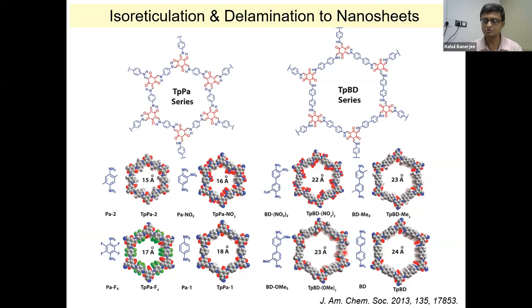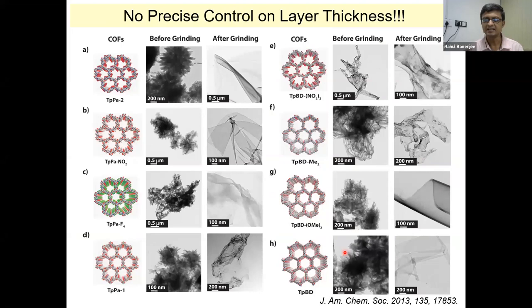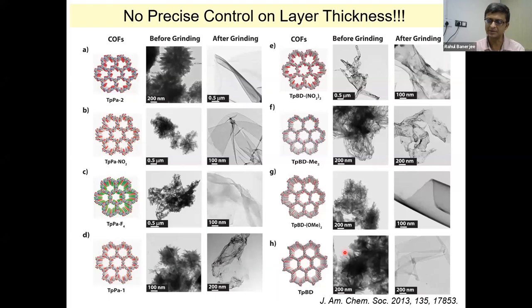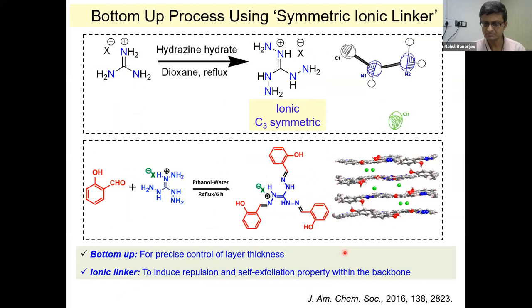We went ahead and made such materials in the laboratory. These bulky powdered structures flatten up like a rolled newspaper when you remove the rubber band — they open up and give you a layered structure. We did solid-state NMR, IR, porosity, and other studies to confirm the local structure, though crystallinity was not very high. However, that does not solve the problem — it still resulted in lots of stacked layers one after another. So we thought to restructure the whole approach and try to break it from the core itself, like a bottom-up synthesis.